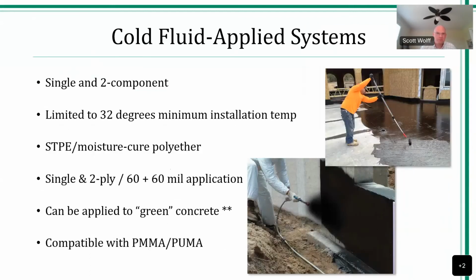Cover those other points. Cold fluid applied, most often are going to be a single component. However, there are some plural component products out there. These are generally limited to about maybe 30, 32 degrees ambient and substrate. Check with manufacturers. And some of these actually incorporate silyl terminated polyether, which make them a little bit more compatible with a wider variety of materials.